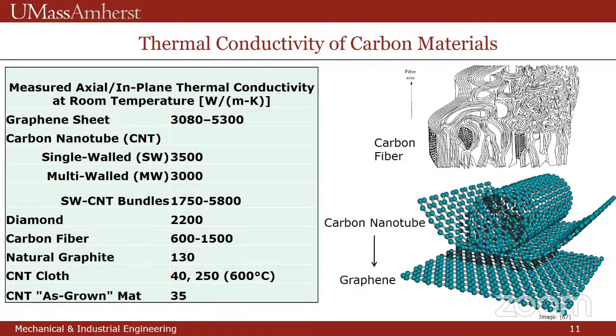So we have available some high thermal conductivity graphite or carbon fibers that are here up to about 1500, about half the thermal conductivity of the carbon nanotubes. And these are macroscopic. So the structure looks kind of like the cartoon. If you imagine rolling up graphene like a newspaper, then you understand the structure of these high conductivity carbon fibers. And by the processing, they make the domains quite large so that you get this high thermal conductivity.